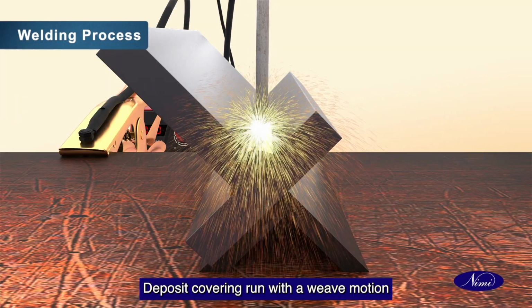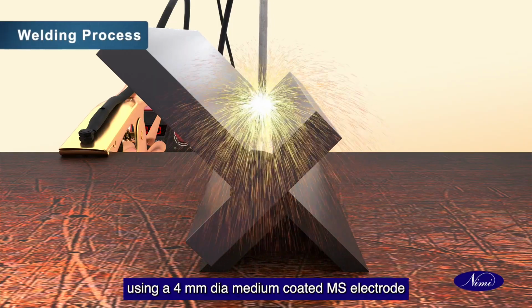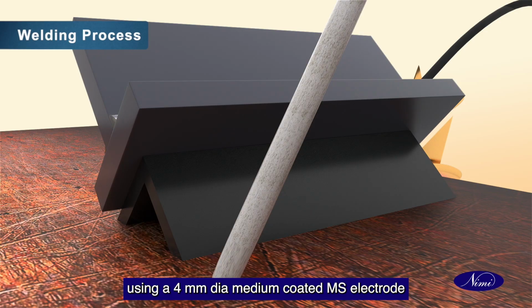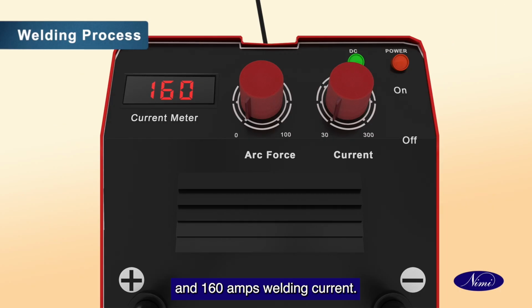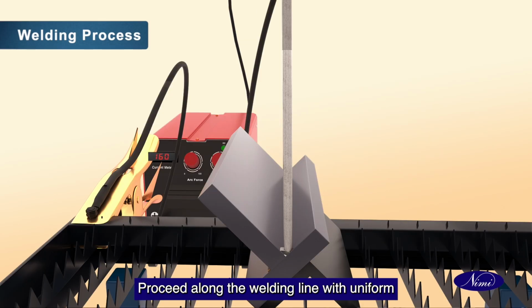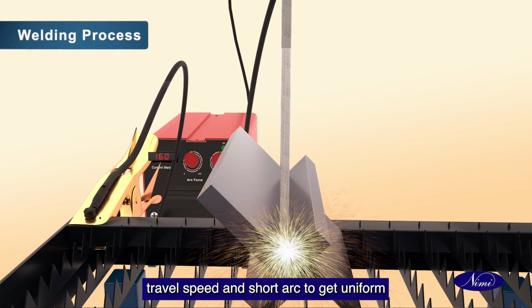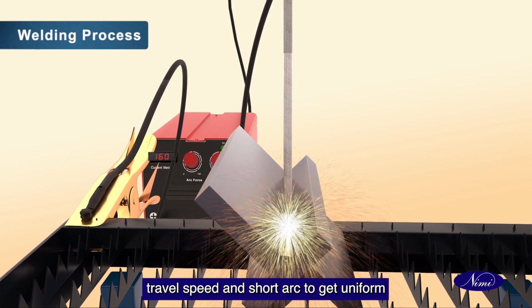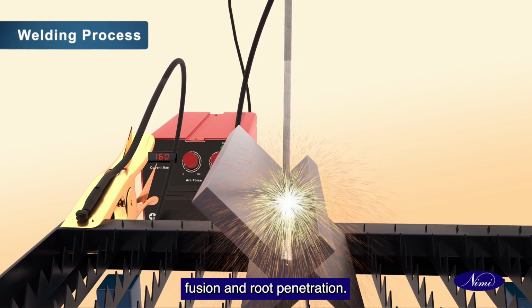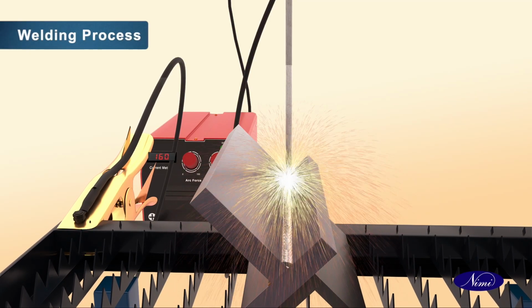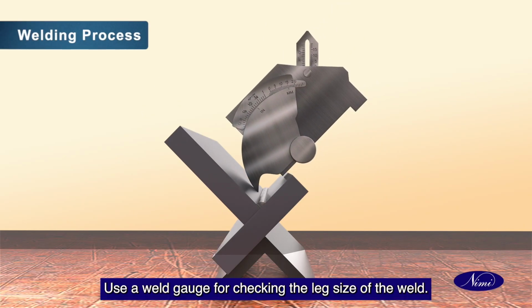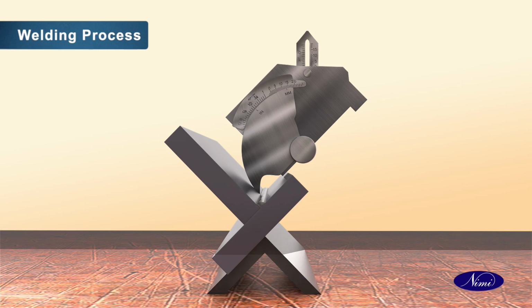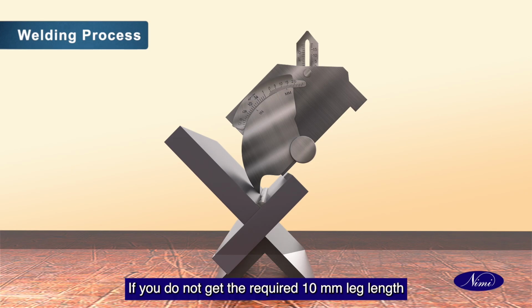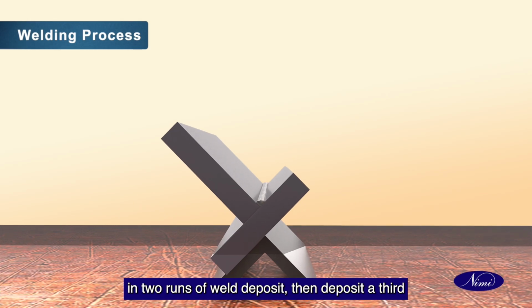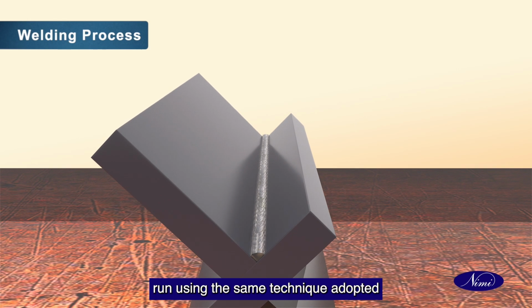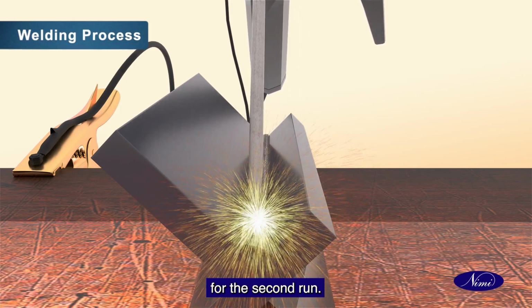Deposit covering run with a weave motion using a 4 mm dia medium coated MS electrode and 160 amps welding current. Proceed along the welding line with uniform travel speed and short arc to get uniform fusion and root penetration. Use a weld gauge for checking the leg size of the weld. If you do not get the required 10 mm leg length in 2 runs of weld deposit, then deposit a third run using the same technique adopted for the second run.